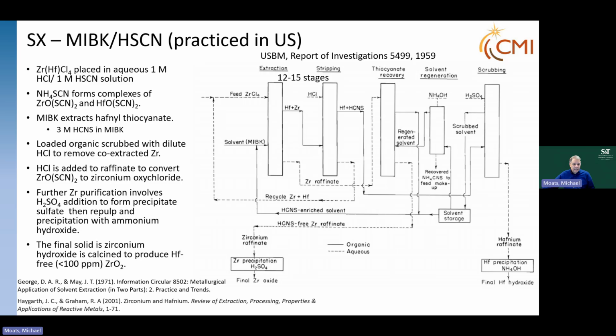The organic, which has hafnium in it, has to be recovered. So the hafnium is stripped using sulfuric acid. The organic is then regenerated, and the MIBK that's saturated with thiocyanate comes back around. So there's extraction, stripping, scrubbing, solvent regeneration, and thiocyanate recovery. It's a fairly complex system, but we end up with hafnium that typically has about 0.5 to 1% zirconium. You can get it lower, but you have to do more purification.